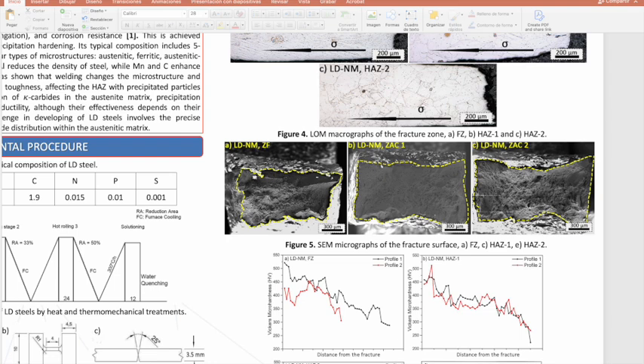Two areas were observed, Zone 1 and Zone 2. Zone 1 was predominant and was characterized by its irregular shape, with pronounced relief concentrated around the dimples that showed coalescence between them. This behavior is associated with a higher degree of ductility in the alloy. Zone 2 is characterized by flat surfaces. The reliefs in this zone are thinner, and there is also a smaller number of dimples on the fracture surface due to the dendritic structure generated.